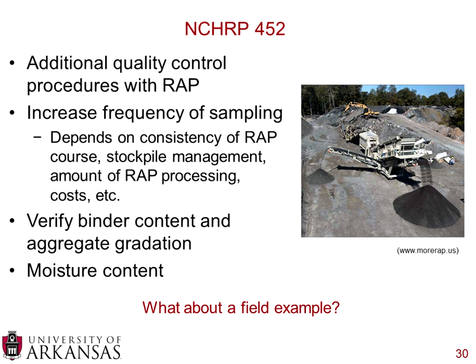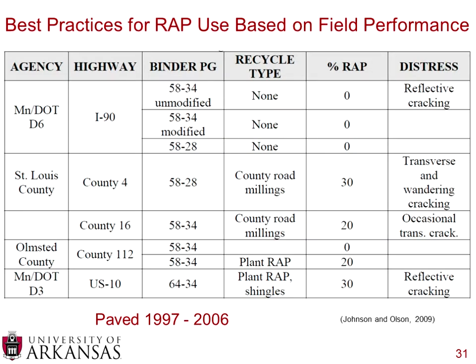They recommend that as you're sampling your material, you want to verify the binder content and the gradation. I think another thing that you can add here is also verifying the binder type. So go ahead and extract that asphalt cement from the RAP, and you're able to verify that you're getting a consistent added binder grade to your material. And then also they're very concerned about the moisture content. So just a couple different reports there from NCHRP, looking a little more at the quality control of plants, ensuring that you're getting a consistent, high-quality product that you can add to your design.